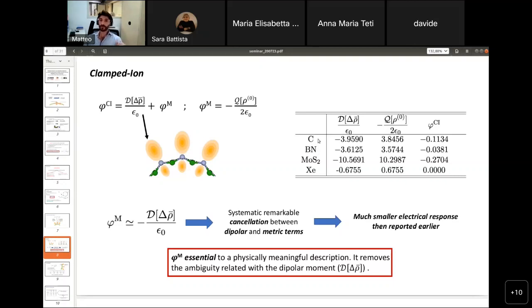Now, take a look at the table. Very interestingly, we find that there is a systematic, remarkable cancellation between the dipole moment and the metric term, leading to a much smaller electrical response than reported earlier. This also tells us that considering the metric term is essential to provide a meaningful description of the effect.